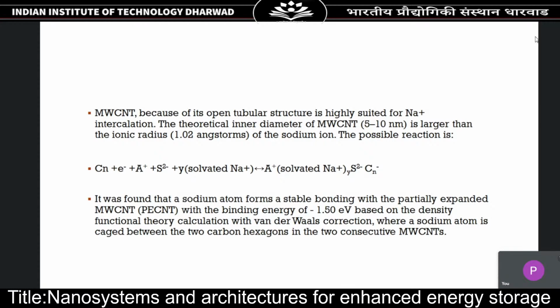The reason why sodium has a very good affinity for carbon nanotubes is that it forms a stable bonding with the partially expanded multi-wall carbon nanotube, and it has a negative binding energy, which shows that there is an attraction between the sodium ion and the carbon nanotube. So that makes it very easy for intercalation and deintercalation.